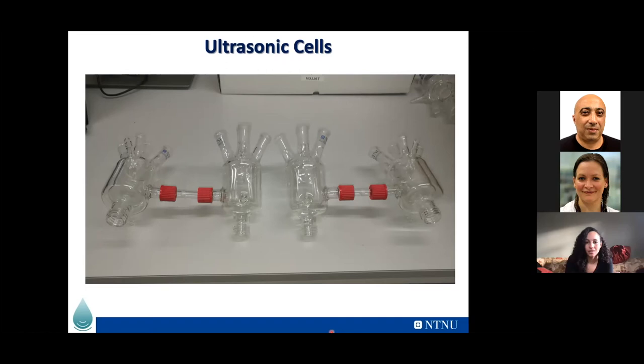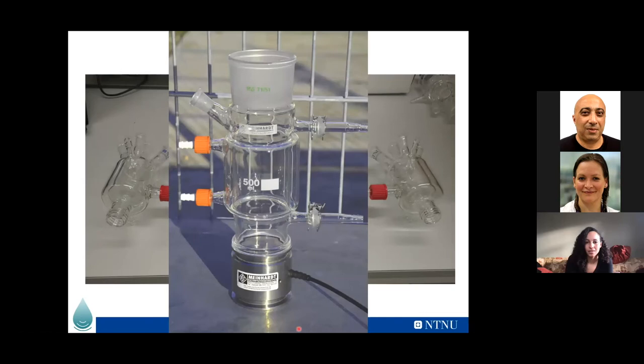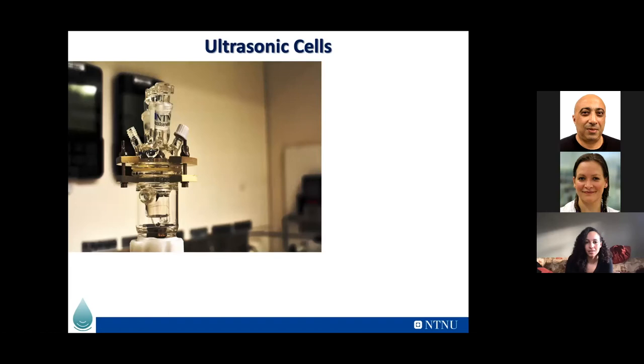You have other systems here, from Meinhardt, a German company, where you have your transducer plate at the bottom that could vibrate from 20 kilohertz up to, let's say, 1 megahertz. Then you have other systems, for example the work we've been doing producing nanoparticles or electrocatalysts in a small volume, where this volume was not in contact with the sonicator, the vibrator, and this area is subjected to ultrasound but with no contact from the probe.